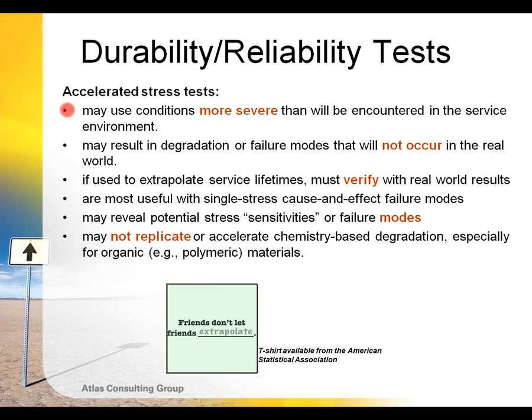However, the use of higher than expected stresses may result in some degradation or failure modes that simply will not occur in the real world. So if you're using short-term elevated stress data to try to extrapolate or predict service lifetimes, you must do some additional testing to validate those assumptions.